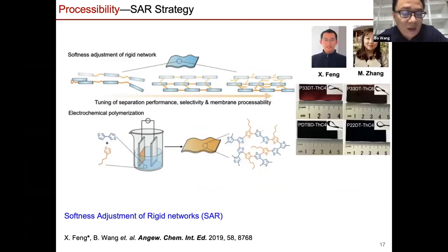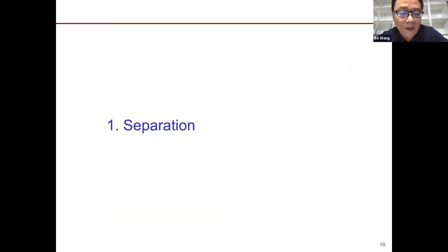And also, we tried other different methods. In this case, it's an electrochemical polymerization process. But in this case, it's not crystalline. But we are trying to introduce different side chains. In this case, the softness adjustments of such a rigid framework can give you a rather flexible membrane. We get a very, very soft, flexible, robust membrane using this method for gas separation. Now let's move on to the separation part.